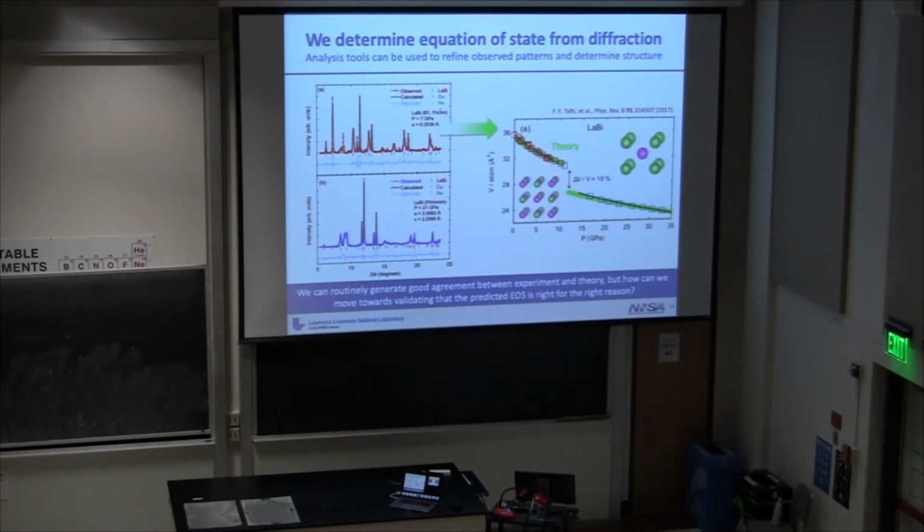If you're used to looking at diffraction patterns, we tend to run things at about 30 kiloelectron volts, so that's about 3 times higher than copper. And so what that means is we go out to something like 22, 24 degrees in 2 theta, but if you expand this out and map this onto the copper diffraction lines, this goes out to about the equivalent of 90 degrees or 100 degrees or something like that. So by going to the high energies, you compress your scattering cone from a 90 degree or a 120 degree scattering cone down to something that's about 20 degrees. So it's actually helpful for the geometry of the diamond anvil cell as well, because we're kind of aligned along that compression axis. But this is what you end up with, diffraction lines.